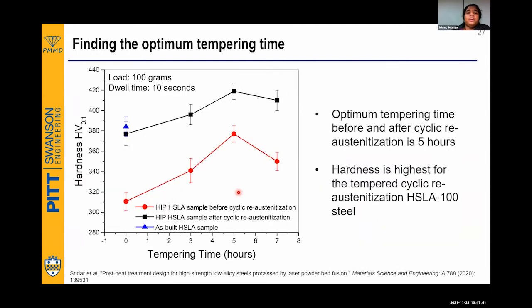So after doing heat treatment at several different times at 550 degrees C, for both before cyclic reaustenization and after cyclic reaustenization, we find that 5 hours is the optimum tempering time. These are all microhardness measurements, which are done with a load of 100 grams and a time of 10 seconds.